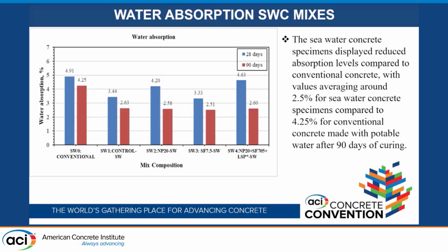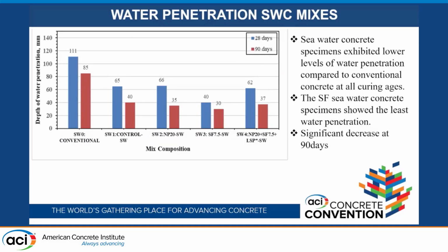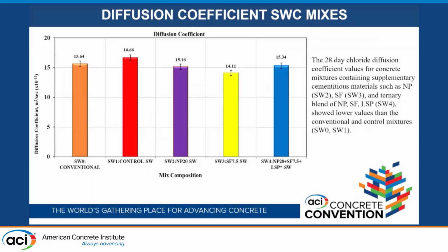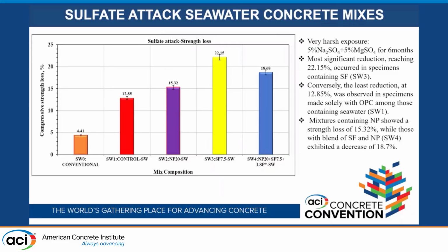Coming to the water absorption, the seawater concrete specimen displays reduced absorption level compared to the conventional concrete, with average values around 2.5% for the seawater concrete specimen compared to 4.25% for the conventional concrete made with the potable water. And water penetration also reduced significantly. Diffusion coefficient was measured and almost of a similar level, no significant changes were seen in the diffusion coefficient.